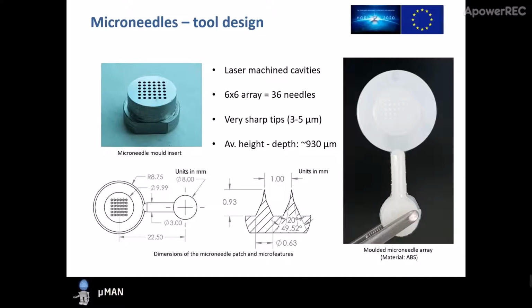So our case study was microneedles, and we use this microneedle mold insert that you see in this image. We have laser machined cavities, which were laser machined at the University of Birmingham. We have a 6x6 configuration of 36 needles in total, and we have very sharp tips, 3 to 5 microns in tip radius, and we have approximately 930 microns of needle height, or cavity depth, for these microneedle cavities.